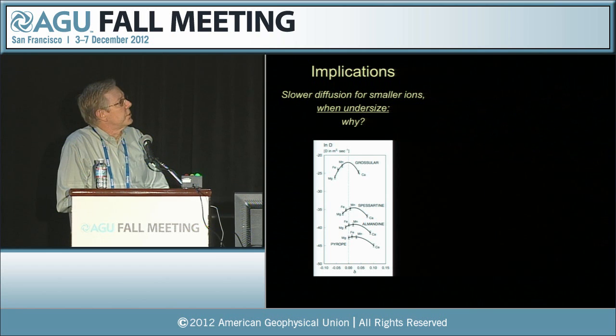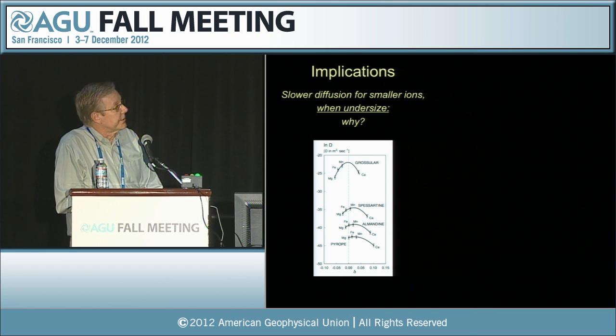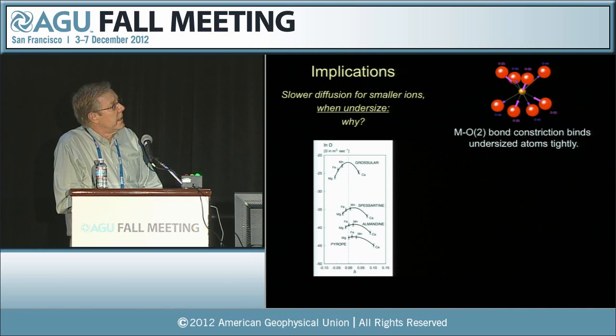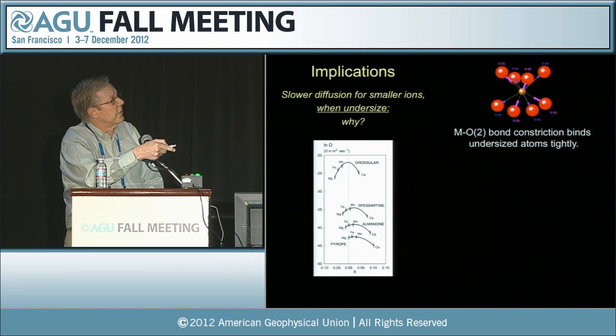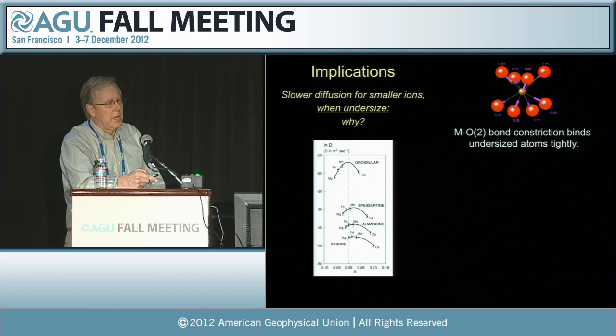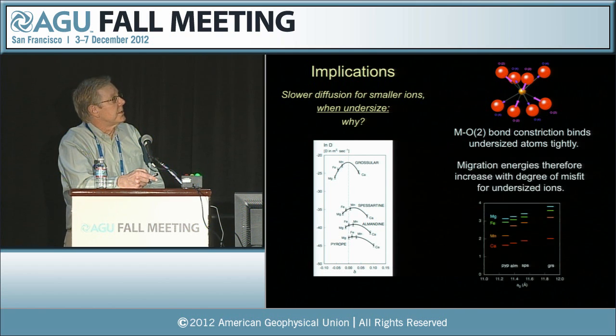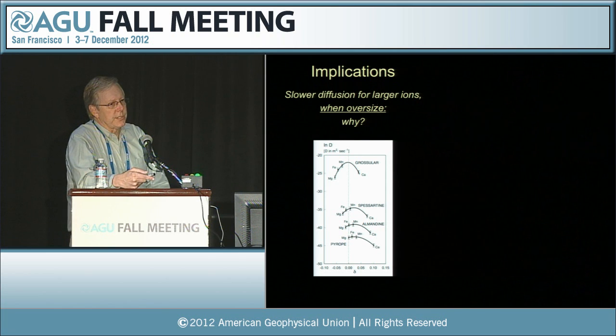We observe slower diffusion for smaller ions when they are undersized on the left side of that diagram. Why is that? Well, the answer is that this constriction of bonds between M and O2 oxygens binds those undersized atoms more tightly within their sites. And so those migration energies therefore increase with the degree of misfit for undersized ions. So that would explain why we have this decrease in diffusivity for smaller ions on the undersized portion of the diagram. On the other hand, we see slower diffusion for larger ions when those ions are oversized.